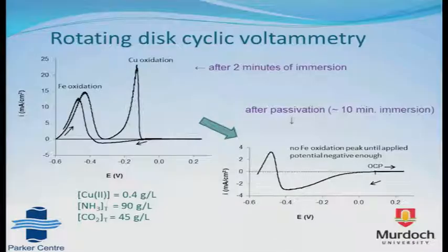When after passivation, you don't get this behavior because the iron is passive. So we're starting from a potential of about 0.1, where I've marked OCP, and we'll get no current because the iron is actually, in fact, passive. This confirms that it's passive. You only get reactivation when you scan it in the negative direction and make it more cathodic. Then you get reactivation of the iron.